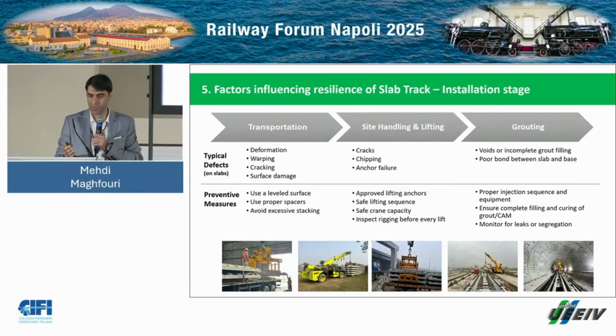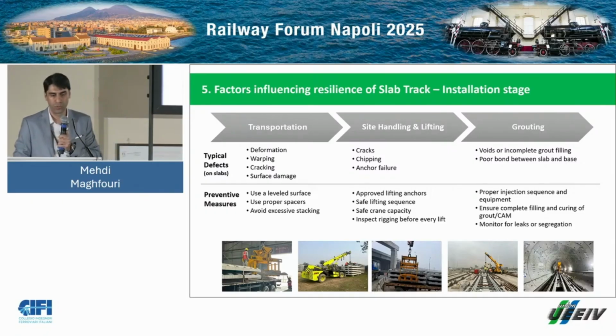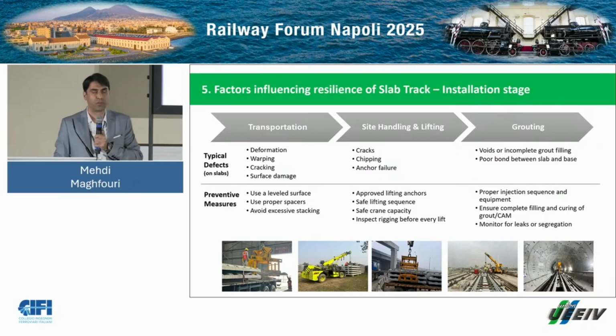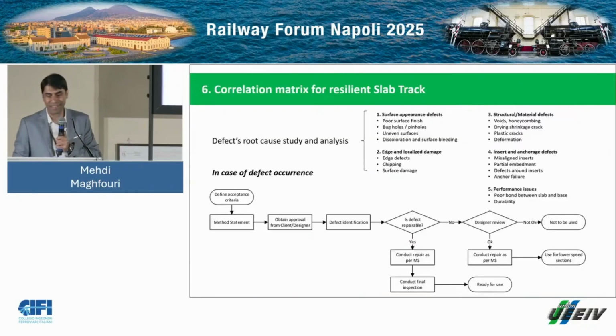And then the transportation: some cracking and surface damage also happen during transportation. Use a level surface, use proper spacers, and avoid excessive stacking. And then site handling and grouting. So these items must be considered to avoid the defects.